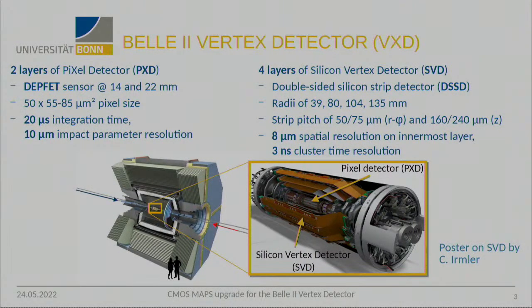Coming to the vertex detectors, we have the pixel detector in the center at very small radii. These are 2 layers of DEPFET technology surrounded by 4 layers of silicon strip detector. The most important figures are that the pixel detector on DEPFET technology has an integration time of 20 microseconds, which is 2 complete beam turns. With this detector we achieve a 10 micrometer impact parameter resolution, while the innermost SVD layer can achieve 8 micrometer spatial resolution and 3 nanosecond cluster time.